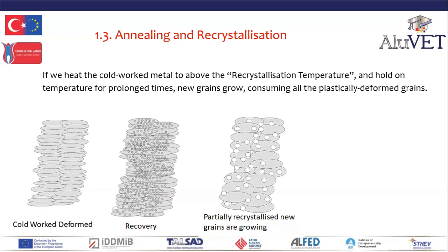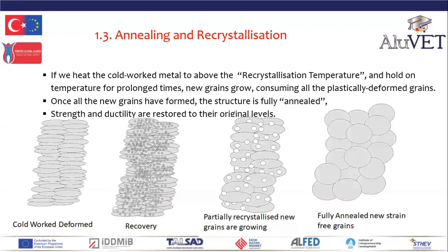Thus, through controlling the degree of recrystallization of strain-hardened structures, we can control or adjust the strength and the ductility of non-heat treatable alloys, 1, 3, or 5000 series. After holding for long periods of time above the recrystallization temperature, eventually all the strain-hardened grains will have been consumed and new grains will have formed. The microstructure is now fully annealed. Strength and ductility have been restored to their original conditions.